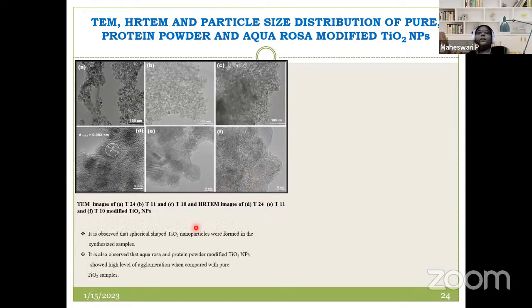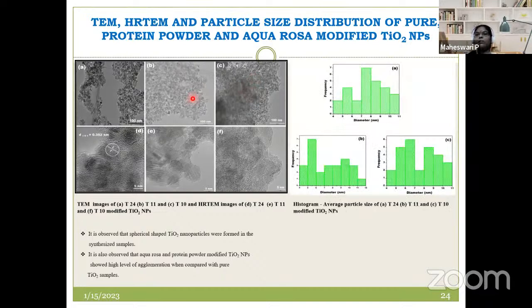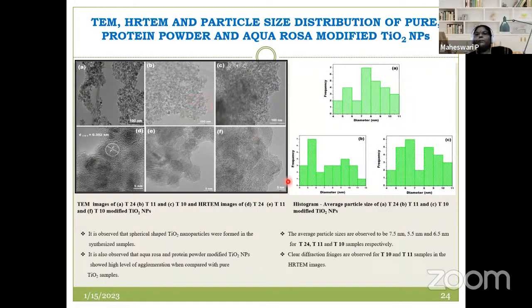So in all of them, you can see there is a spherical shaped TiO2, and when the modifiers are added over it, there is a high level of agglomeration, which you can see over here. The particle size has been estimated to be 7.5 nanometers for the synthesized one, 5.5 for the protein powder modified one, and 6.5 nanometers for Aquarosa.